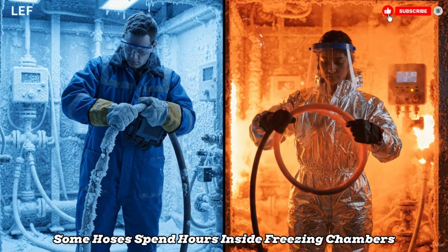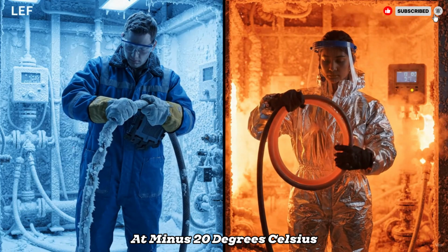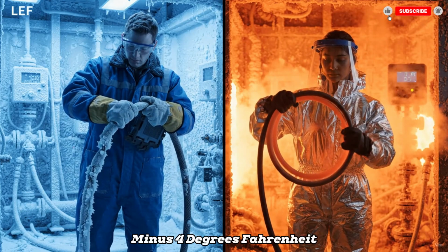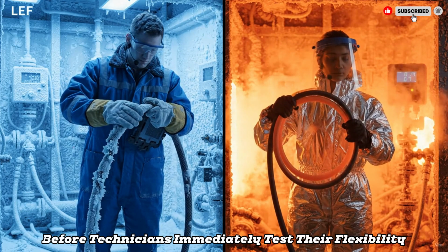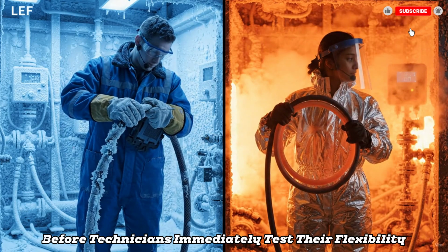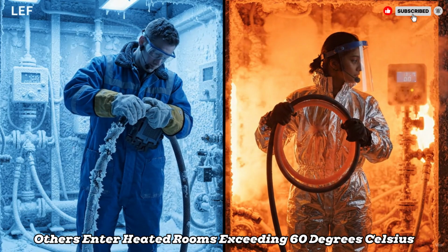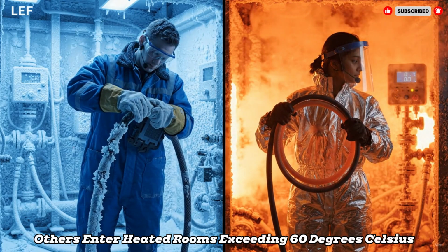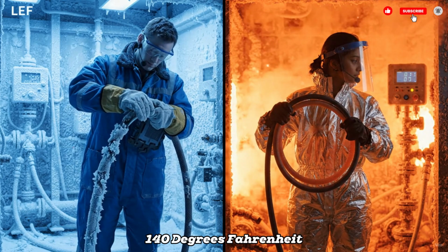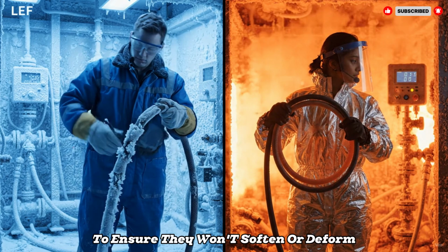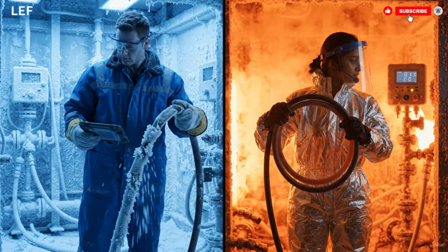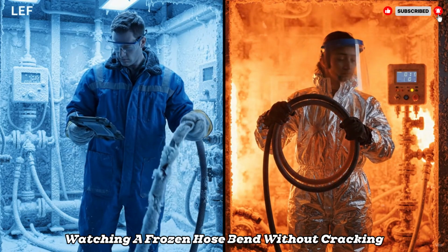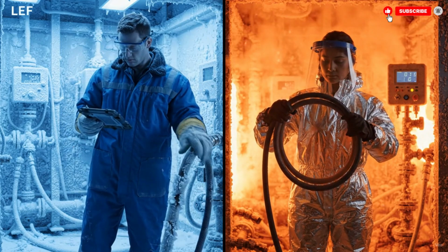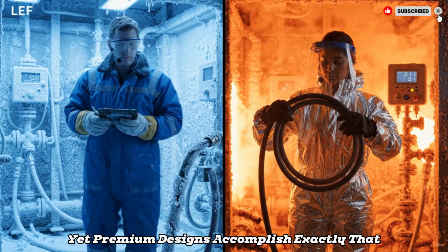Extreme temperatures create another hidden challenge. Some hoses spend hours inside freezing chambers at minus 20 degrees Celsius, minus 4 degrees Fahrenheit, before technicians immediately test their flexibility. Others enter heated rooms exceeding 60 degrees Celsius, 140 degrees Fahrenheit, to ensure they won't soften or deform during the hottest summer afternoons. Watching a frozen hose bend without cracking feels almost impossible, yet premium designs accomplish exactly that.